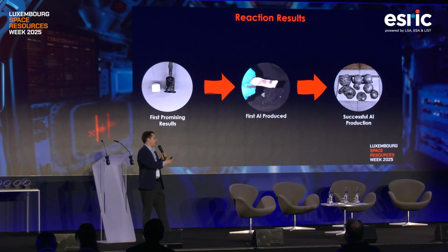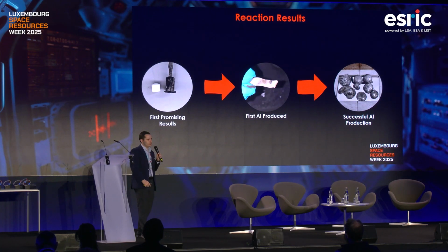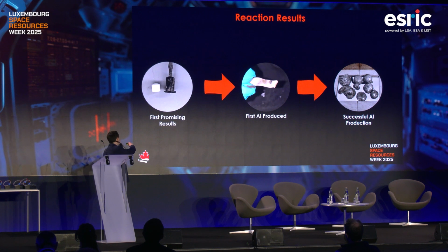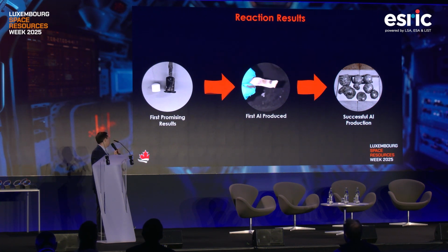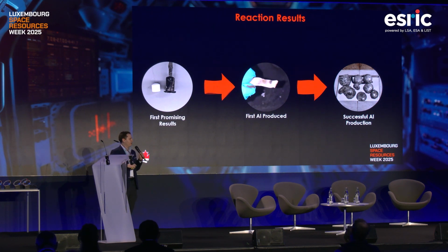So these are some of our results from electrolysis. The first image shows our first promising results. Basically, we have a comparison of one of the pellets that we were using on the left side. You can see that it's very white. And on the right side, you can see one of our electrodes with the pellets, and you can see that there's a metallic surface or a metallic coating. We did the chemical analysis, and we found that we had produced around 10% aluminum. But we weren't able to produce actual metal by itself.